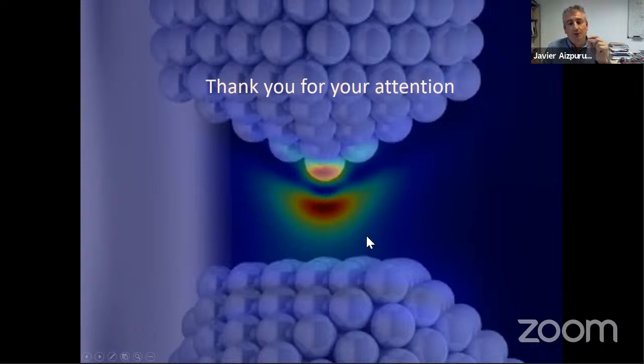So the secret of all these scanning tunneling microscopy groups, Saint-Chaudon in Hefei, Guillaume Schull in Strasbourg, Wilson Ho in California, Richard Berndt in Kiel, all these groups, four or five groups who do this in the world, they managed to find that if you put a sodium chloride monolayer, an atomic monolayer, separating the metal and the molecule, one is not enough. It's still quenched. Two, it's in the limit. And with three monolayers of sodium chloride, the molecule loses the direct quenching coupling with the metal, and it lives sufficiently to emit to the far field. So the two to three sodium chloride monolayers are absolutely essential to get this electroluminescence or photoluminescence from the tunneling junction.